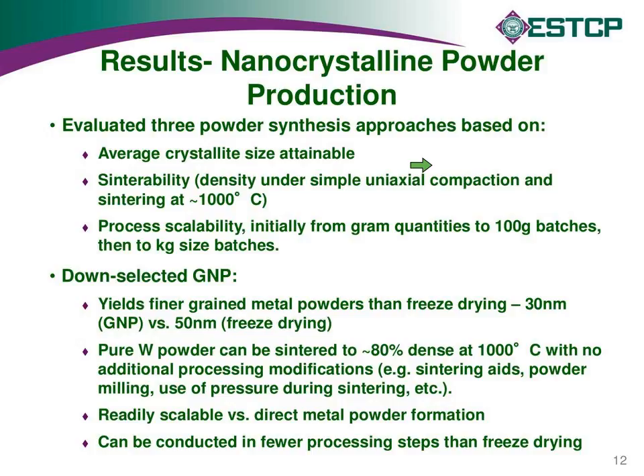Our criteria were, how fine a grain size powders could we produce, how sinterable were those materials, and how scalable was the process going to be. Eventually, we down selected to the glycine nitrate process because it did produce the finest tungsten crystallites, averaging around 30 nanometers, where they were like twice that size with the freeze-dried process.